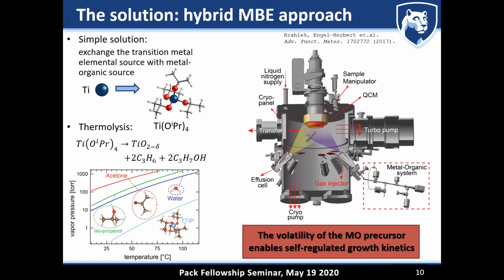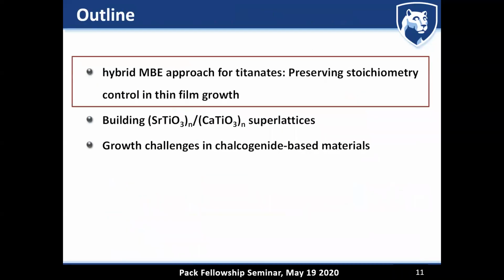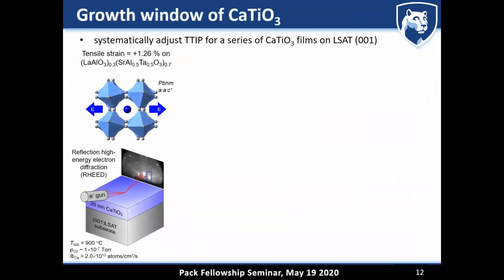And so this is the hypothesis, this is the idea. And what I'm going to show you in the next couple of slides is that if you apply this hybrid molecular beam epitaxy approach for the growth of titanates, and specifically calcium titanate, you can actually preserve the stoichiometry as you're growing. And so the set of experiments is relatively straightforward. Imagine you want to grow a 20 nanometer thick calcium titanate film. This is challenging. You're going to mount this on a very specific, structurally matching substrate. In this case, we use the LSAT substrate.